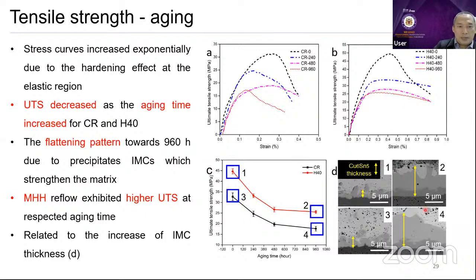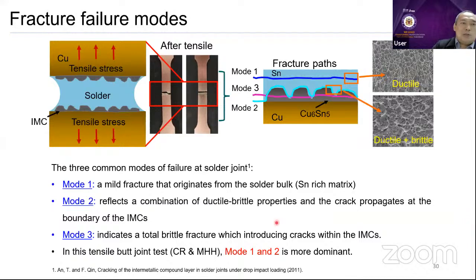And we do the comparison here, as explained, because this one is based on the IMC thickness. I've tried my best to explain this one by using this schematic drawing. The failure of the fracture can be two different modes. It can be from the bulk of the solder, or from the interface between the solder and the IMC. Another one is the failure of the IMC itself. But in our case, it is normally related to mode number 1 and number 2.